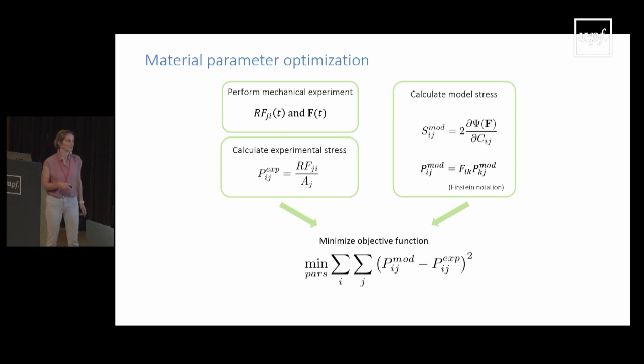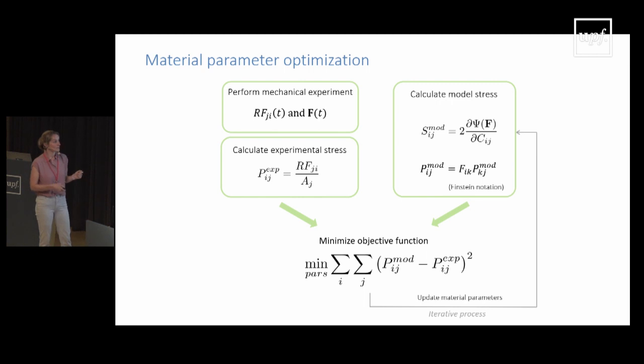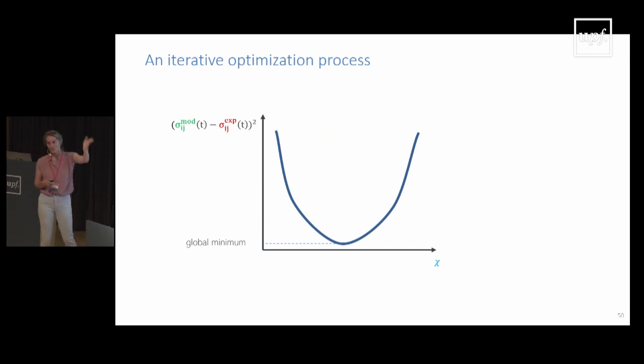So we can minimize the model stress with respect to the experimental stress for each direction in which we did our test. So it could be 2 directions for planar biaxial, it could be 3 if we do triaxial testing, that depends. And we obviously need to update our material parameters until we've reached the minimum of our objective function. So the objective function in a 2D framework would look something like this.